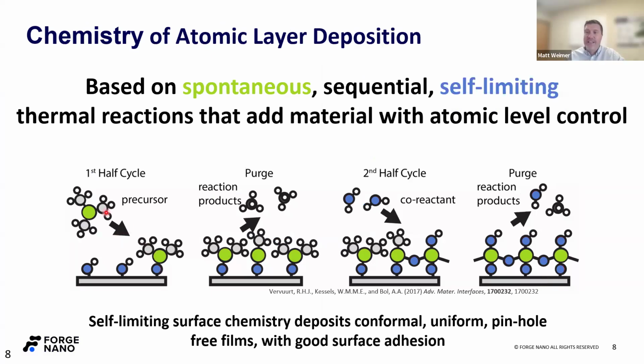So if we briefly walk through this, we've replaced our blue spikes with these molecules here. We'll even call this something specific. This is trimethyl aluminum. These are 3 methyl groups, CH3, and this is an aluminum atom. The surface, those blue little divots, is now our hydroxyl. So when this molecule sees the surface, we move a proton and generate methane. But more importantly, we now have a new oxygen-aluminum surface bond. That's critical because in this process, by definition of ALD, we have really good surface adhesion, so that the film adhesion strength is as strong as those bond strengths, which is a really important thing when you think about the quality of ALD.